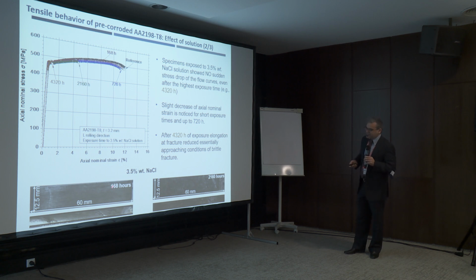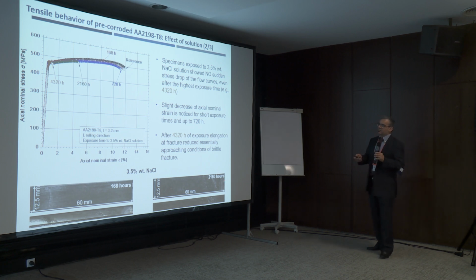After 168 hours, you can see actually no pores, no pitting. But after 2160 hours, when you have increased degradation, then you can, my apologies, you cannot see it. Here there is some localized corrosion very close to the fracture. Here is supposed to be the fracture of the specimen.